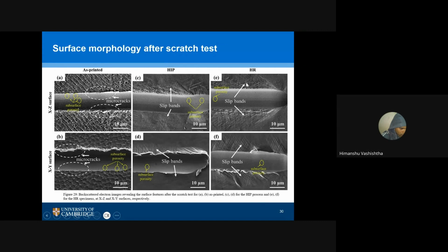In the case of hot rolling, the wear volume has been on the moderate side because the grain size has increased, and the increased grain size is providing strength because of the high number of grain boundaries that are resisting the deformations.